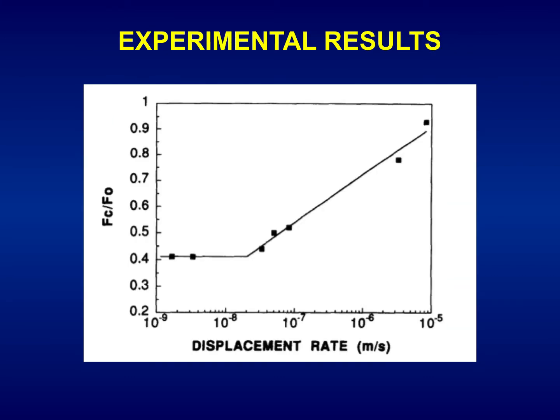This is a plot of macroscopic experimental results: failure load in hydrogen, F_C, critical load in hydrogen, divided by the reference value in fracture in air with no hydrogen assistance, versus the displacement rate in meters per second. We observe the typical increasing monotonic trend of any hydrogen embrittlement, hydrogen-assisted cracking test when tested against the displacement rate, the crosshead speed, or the global displacement rate. There is an increasing trend. The higher the displacement rate, the lesser the effect of hydrogen, because we have less time for hydrogen entrance, penetration, and diffusion into the sample, and less time for hydrogen-assisted damage or for hydrogen embrittlement.